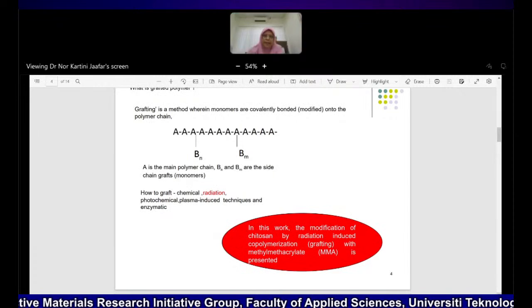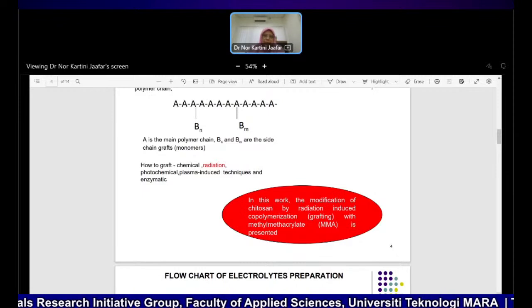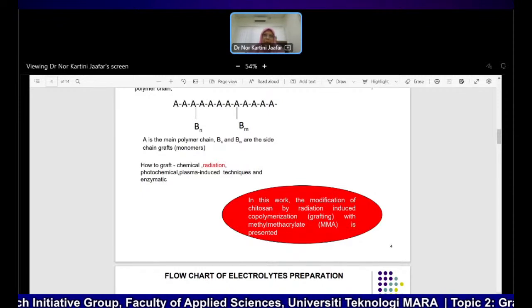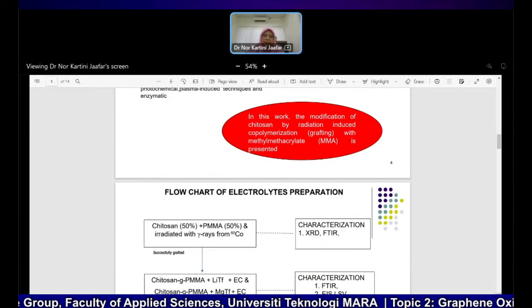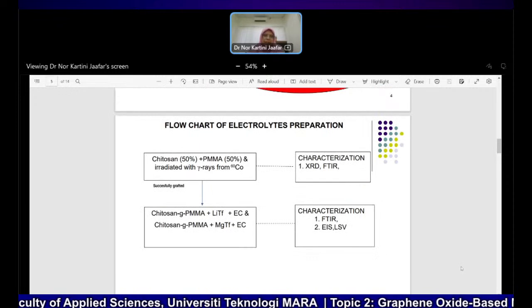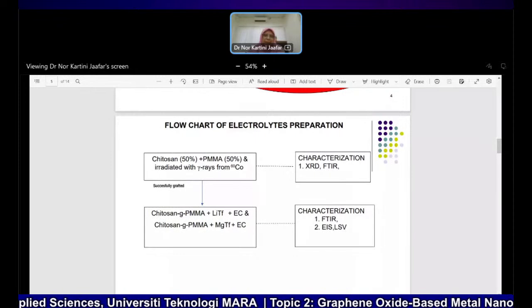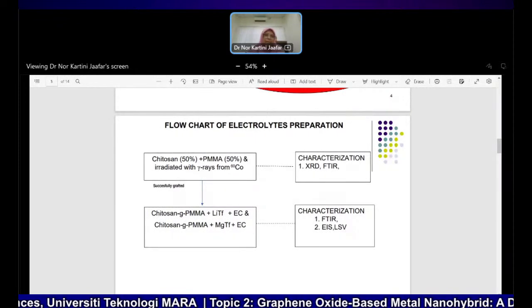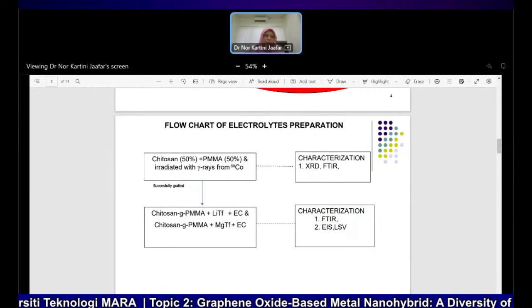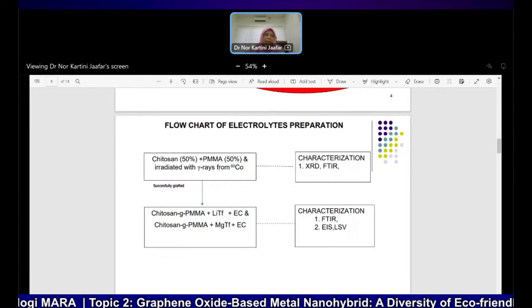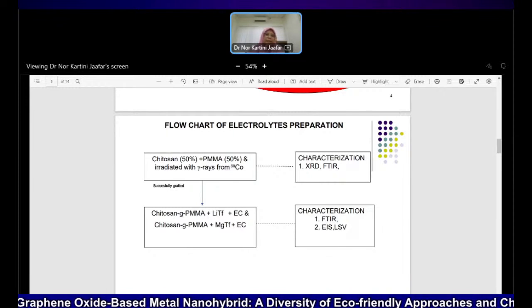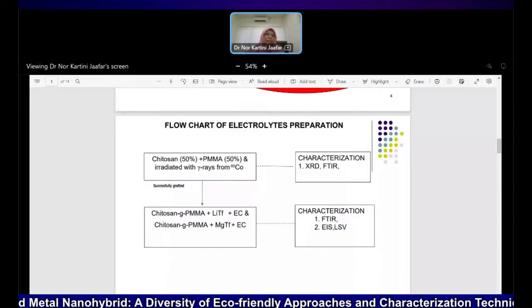So in my work, I grafted Chitosan with PMMA via gamma radiation. This is a simplified version of the preparation method. I first blended Chitosan with the monomer MMA, not PMMA yet, before grafting. Then we send the sample to the gamma ray facility at Nuklear Malaysia, Bangi, to be irradiated with gamma rays.